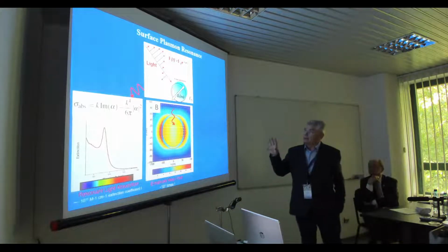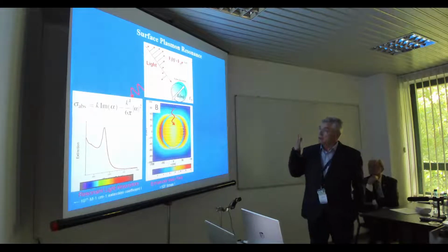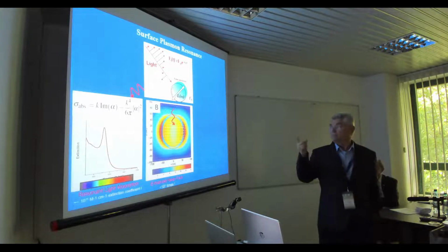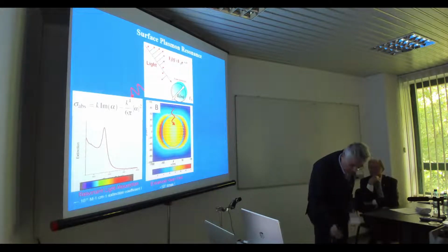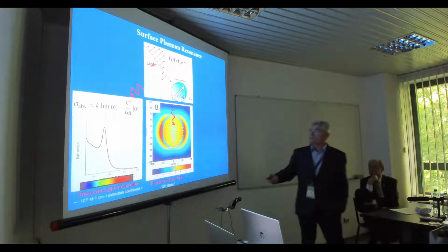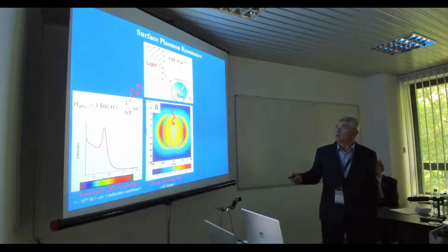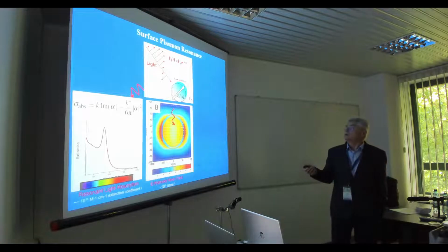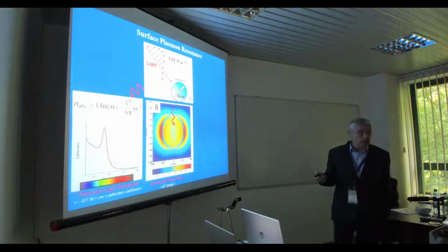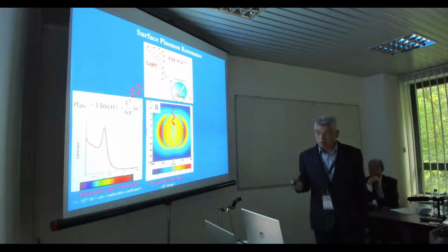But this is not all. There is also light which is absorbed by the particle, and the signature is a spectral absorption spectrum. Here you can see what is called localized surface plasmon resonance for a round-shaped, standard gold nanoparticle. It is very good for sensing: if something happens around the nanoparticle, the resonance will shift.